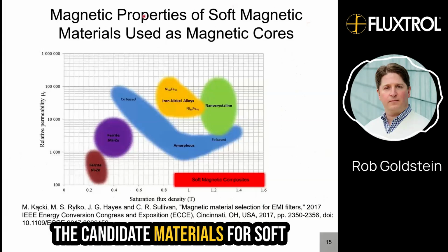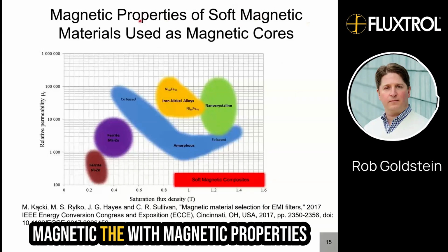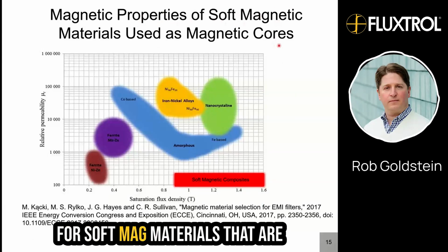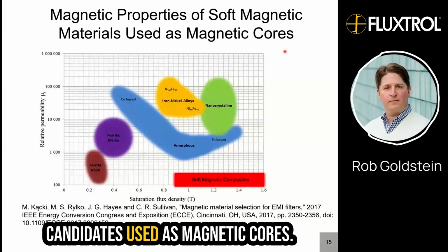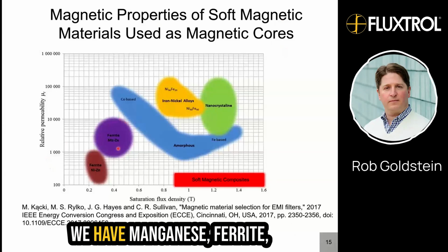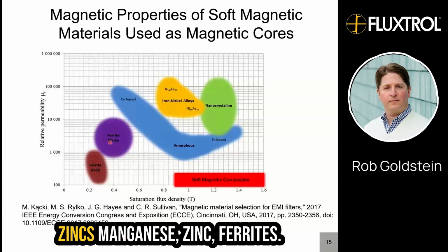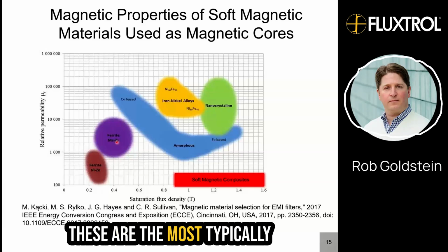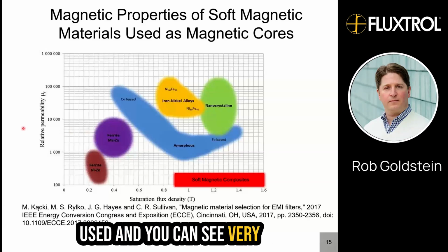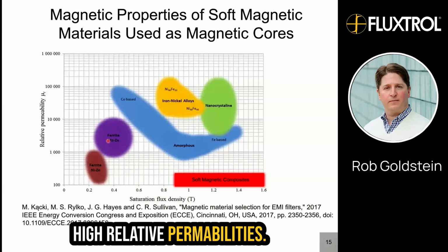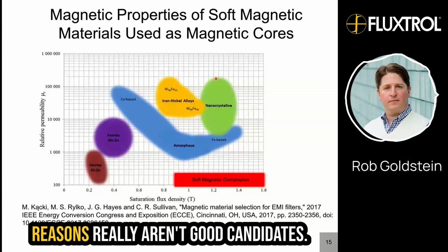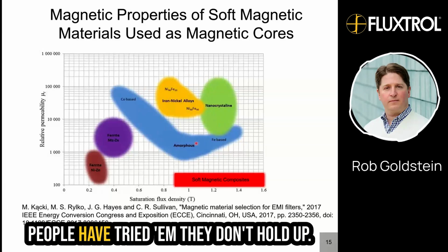The candidate materials for soft magnetic cores, looking at the magnetic properties, are manganese-zinc ferrites. These are the most typically used, and you can see very high relative permeabilities. Now, these other materials, for other reasons, really aren't good candidates. People have tried them. They don't hold up.